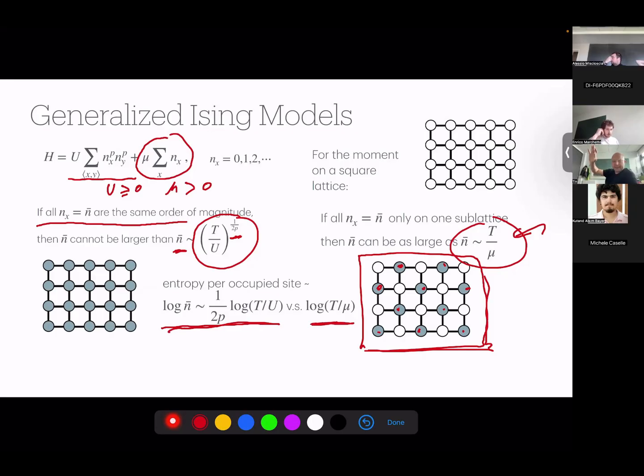Okay, is this point clear? Are there any questions here? What I'm trying to say? I'm simply trying to say, because of the repulsive interactions, when I'm trying to fill the lattice uniformly everywhere, they clash, right? This repulsion forces the maximal spin to scale potentially slower with temperature. If p is larger than 1, as we will see, it will be slower scaling. Whereas if we occupy only half the lattice, such that occupied sites are surrounded by empty sites, then I can go much higher in principle with the occupation. But what I sacrifice is the fact that translation symmetry is no longer realized in this state.